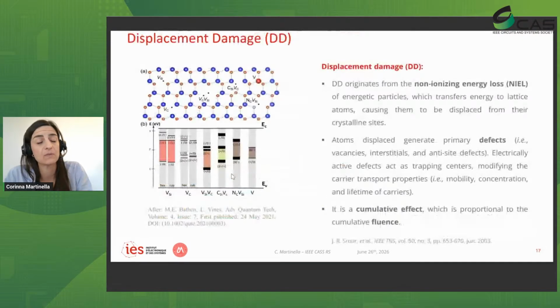Instead, when we talk about displacement damage, this originates from the non-ionizing energy loss mechanisms that the particle undergoes while interacting with the medium. The particle transfers energy to the lattice, and it can displace some of the atoms from the crystalline sites. The displaced atoms can generate primary defects, such as vacancies, interstitials, and antisite defects. Some of these defects might be electrically active, and they can act as trapping centers.